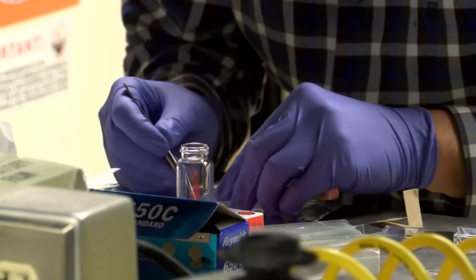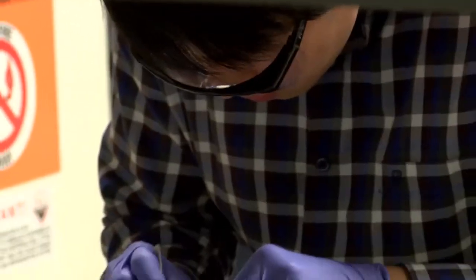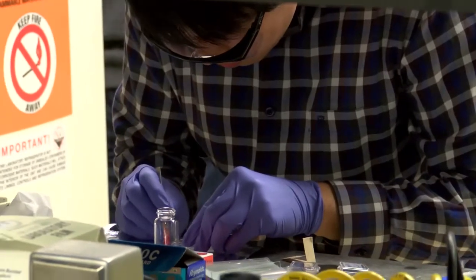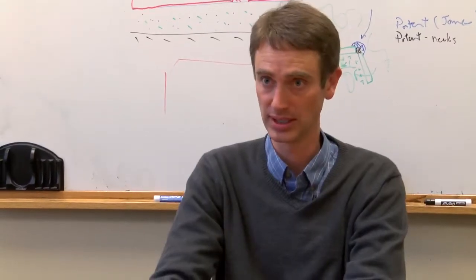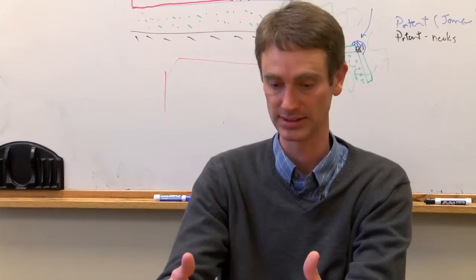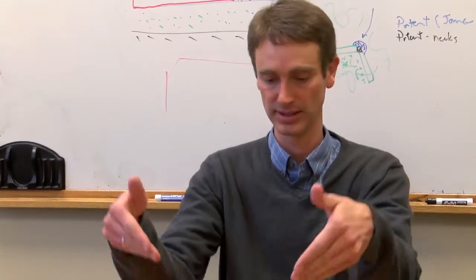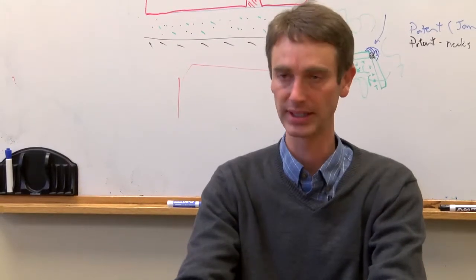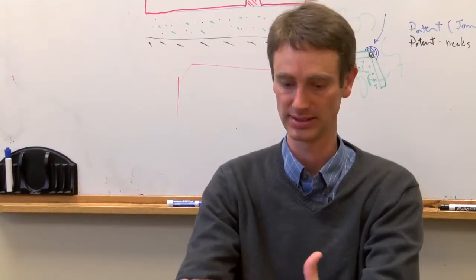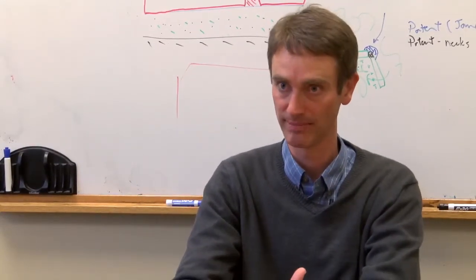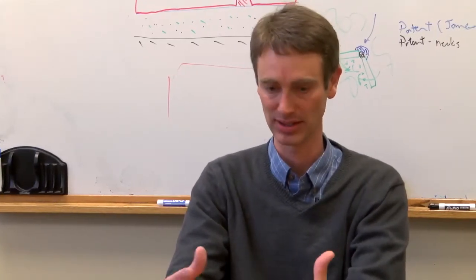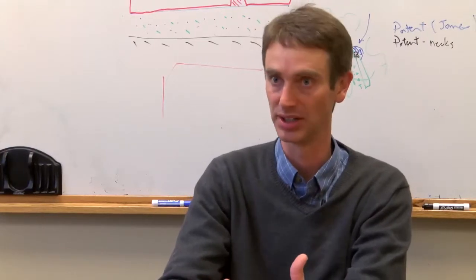So what we realized is we needed a way to be able to 3D print the positive and negative terminals directly onto some substrate. We were able to do this using optical patterning, so taking this light-sensitive polymer, exposing it with light. When you expose it with multiple beams of light, the way that the light interacts creates a 3D pattern in the polymer. We then dissolve away the polymer that hasn't reacted with the light, and so that leaves behind what looks to be like a sponge.